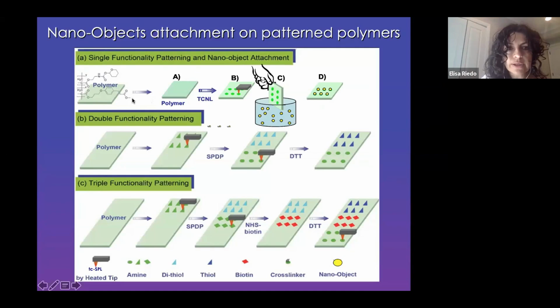This is a methacrylate copolymer, where the functional groups that are exposed after heating are actually amine groups. Now, you follow the same protocols, and you can also think about different bioconjugation steps. So, for example, you can dip in a solution with SPDP and transform your amine groups into thiol groups through a second washing with DTT. Or you can bioconjugate the thiol groups with some NHS biotin, and then have a pattern where the red one is biotin, you have thiols here, and you have amine here. So you have 3 different functional groups.